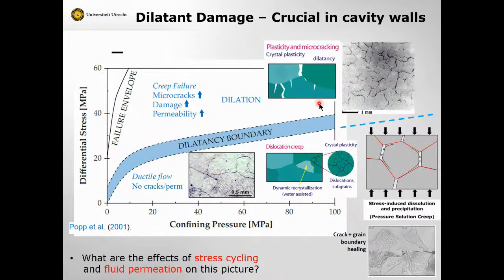Besides all that, there's the additional complication if you look at a field of differential stress and confining pressure. So low differential stress, which is deviatoric stress, and high confining pressures, you do not get dilatancy, and you get dislocation creep, you get recrystallization, you get pressure solution. We can describe this behavior pretty well. But if you start increasing the stress, you get into the regime where dilatancy occurs and the microstructure starts cracking up. You get microcracks, damage. You get porosity and permeability development.